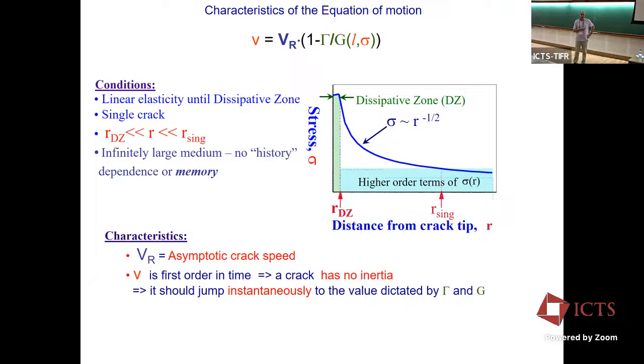So as a crack is zooming along, if, for example, you change the fracture energy, so it goes into a tougher material, instantaneously, this theory tells us that it will adapt its velocity to that material. There's no inertia. It doesn't take time to accelerate or decelerate. Accelerations and decelerations are instantaneous here because there's no V dot here. There's no acceleration term in this equation of motion.